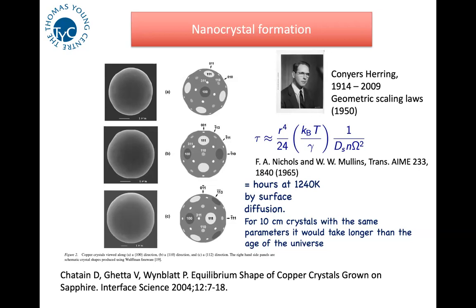These are nanocrystals on this picture. And these are metal, these are copper. And in the experiment, this is Dominique Chatain's group in Luminy, she could actually see facets, Wulff-shaped crystals emerging on these nanocrystals, and you could make an estimate of the relative surface energies of different surfaces. It's pretty crude though, pretty crude estimate. But for this process, for them to form crystals like that, the time scale is much faster because they're so small, and it's a matter of hours at 1240 K. Interestingly, this scaling to the power 4 in these apparently such different scenarios as the sinusoidal surface corrugations and the sphere transforming into a crystal like this, R to the 4th power, was derived completely generally by Conyers Herring back in 1950.